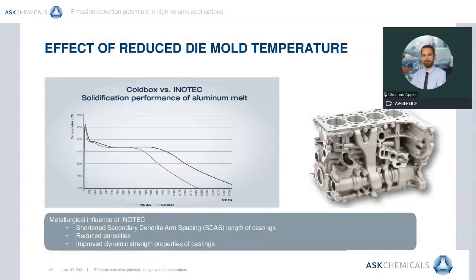Inorganic sand cores exhibit roughly 25% of the gas potential of organic bound sand cores. Thus, the pore percentage in the casting and degree of porosity is dramatically decreased. Both parameters contribute to improved dynamic properties of the casting as metallurgical structures of higher strength and elongation properties result. This effect enables wall thickness reduction and contributes to the overall trend of downsizing and lightweight construction, especially in ICE powertrain applications.